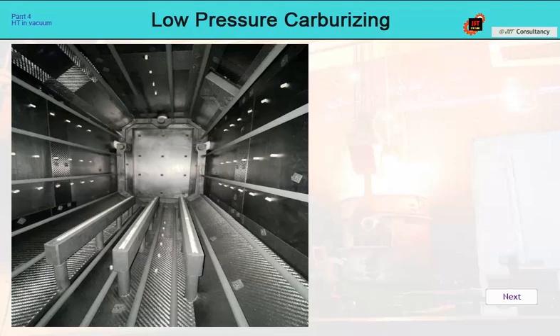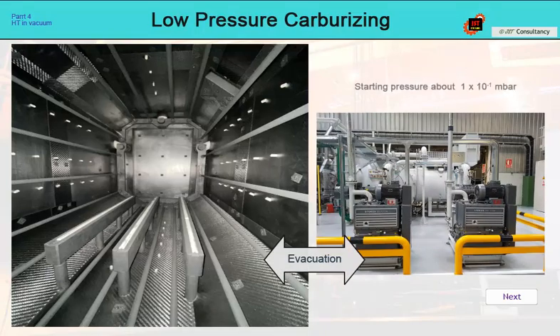In the case of single-chamber furnaces with LPC and quenching in a gas stream, the process begins with the chamber being evacuated to a limit vacuum and gradually heated to the carburizing temperature. However, since the majority of furnaces for LPC are furnaces with 2 or more chambers, the carburizing chamber is permanently under vacuum and permanently at the working temperature. The batch is therefore loaded into the already heated chamber and gradually heated to the austenitizing temperature.